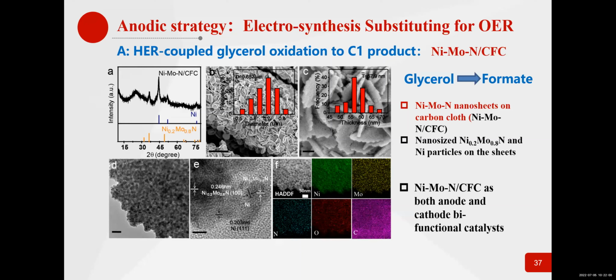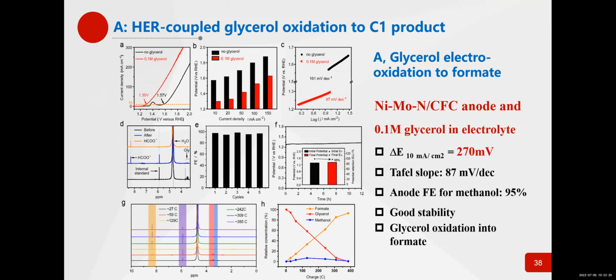This nanosheet is loaded on carbon cloth, so we call it nickel molybdenum nitride CFC. And this kind of material shows flake-like morphologies, and it shows a very high surface area. And you can see that by using this kind of material as the catalyst at the anode, and by adding glycerol as the substrate for its oxidation to replace OER, the overpotential at the anode can be reduced by as much as 270 millivolt, and the Tafel slope is also relatively low at 87 millivolt. And then we can see that during the process, we can obtain the formate from the oxidation of glycerol.